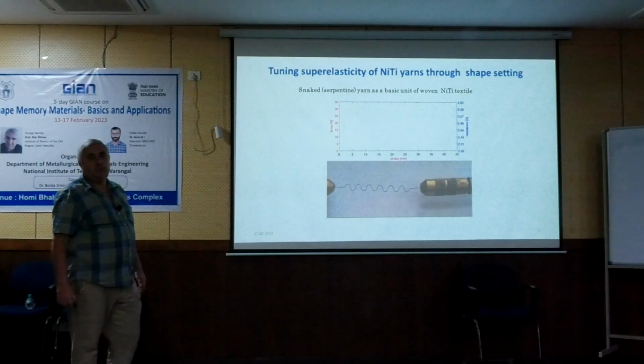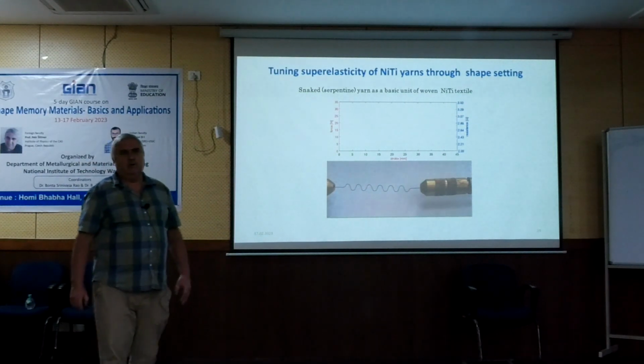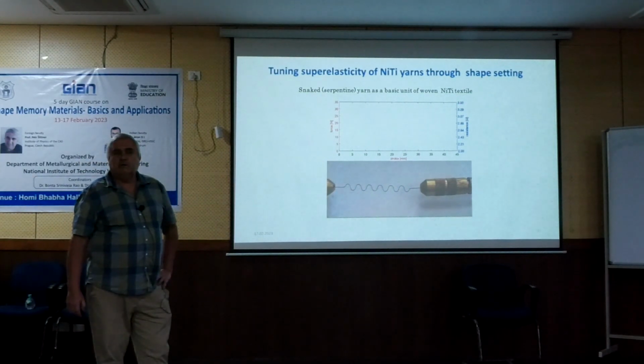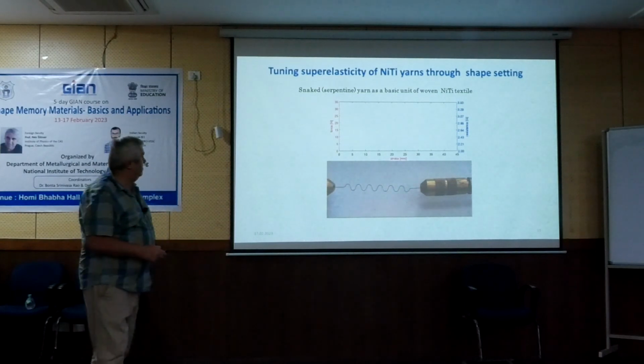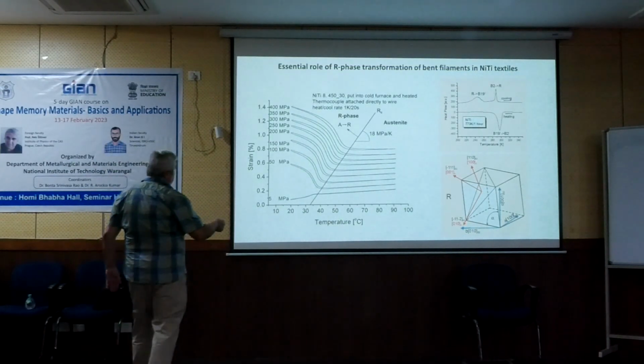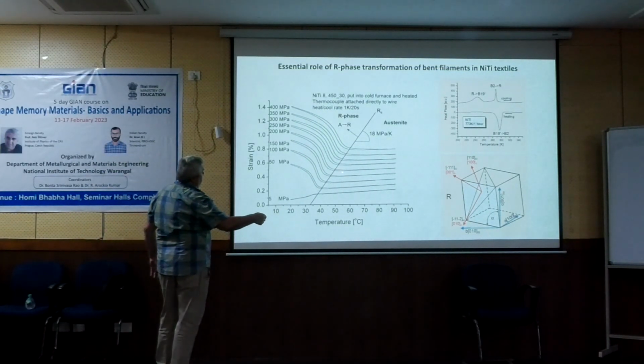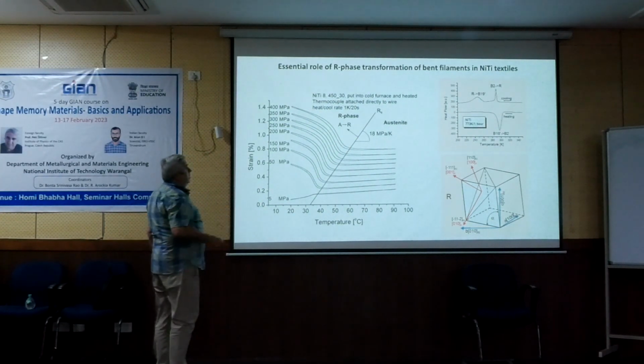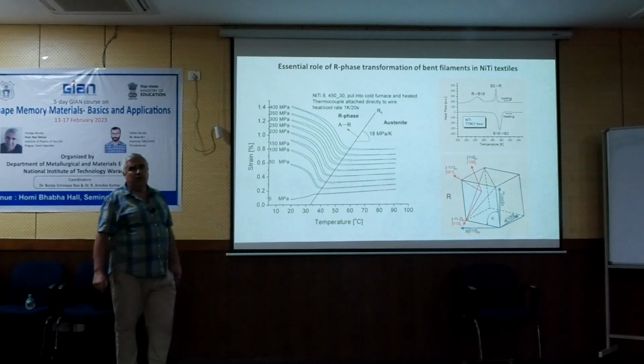On cooling, the B2 to R phase transformation is playing the role. Reverse here only. What is the transformation responsible for this? This is cooling, heating, due to the R phase. The strain is like 0.5% here, and here it is like 1%. In application also, only the B2 to R phase transformation is being used?